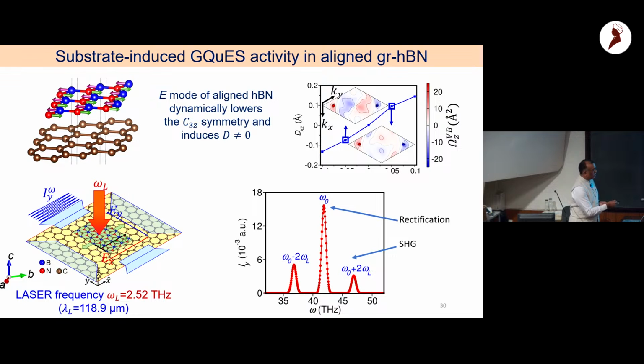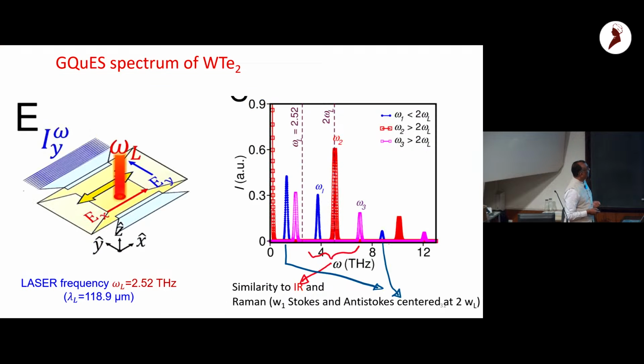In fact, you have one peak which is associated with the E vibration, which is at 41 terahertz, and then you have two other peaks which are Stokes and anti-Stokes peaks associated with the fact that energy is pumped in from 2 times omega L. That's basically the 2 times omega light, because that's the pumping frequency in this kind of experiment. Okay, so the same ideas can be, I'm almost getting over time, so I'll close now with this slide.